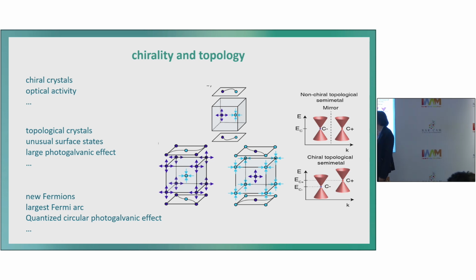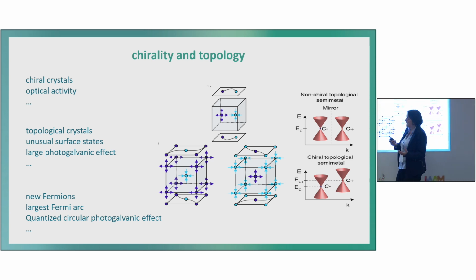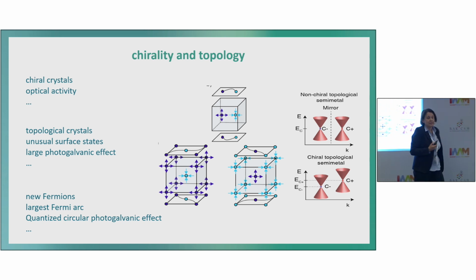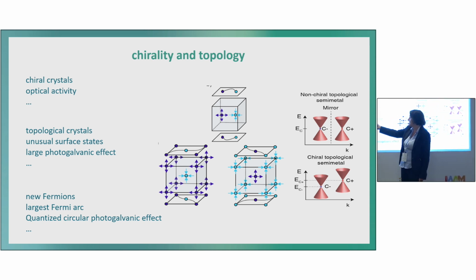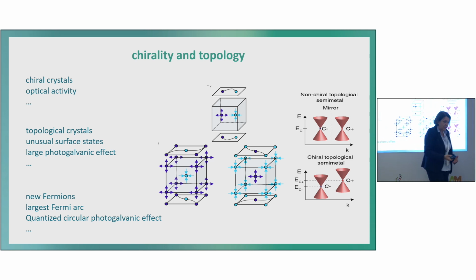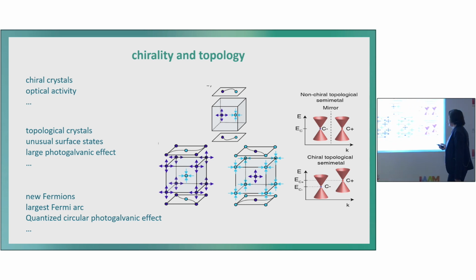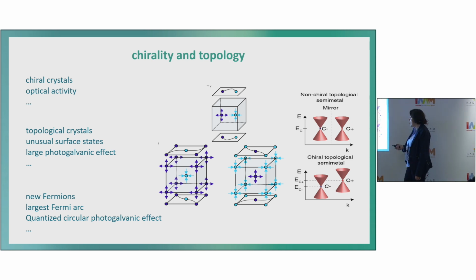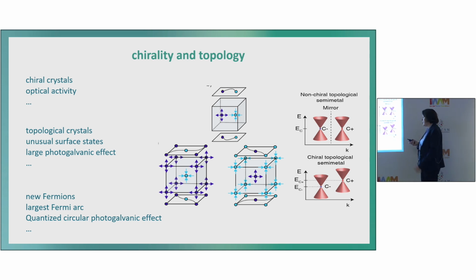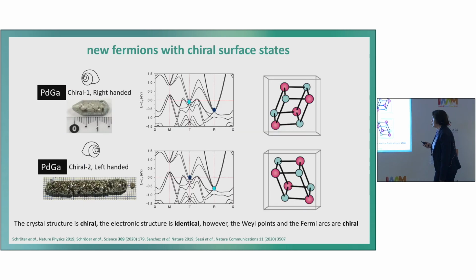Anyway, here we combine chirality and topology. People who are interested in chiral crystals are always interested in nonlinear optical properties, so we can maybe combine this unusual surface state, and I already talked about this photogalvanic effect, which is extremely large and also depends on the chirality of the light, so we can have totally new effects. The major difference between Weyl semimetals and these chiral topological semimetals is that the chiral points are at different energies, so they spread over a much larger energy range, and therefore we can expect new properties, even like a quantized circular photogalvanic effect.